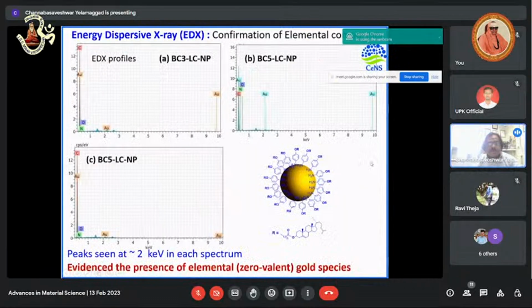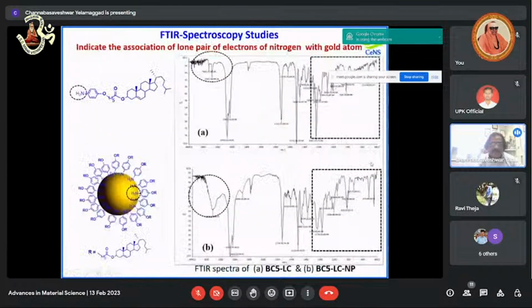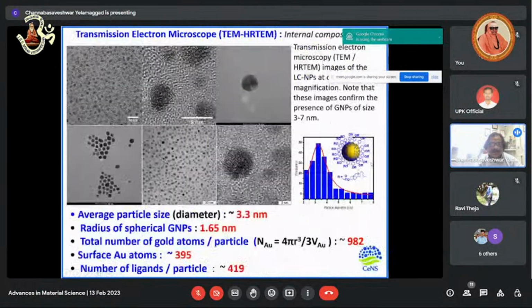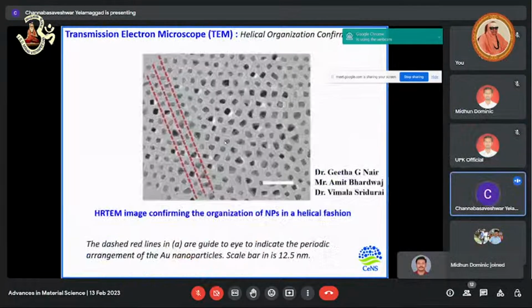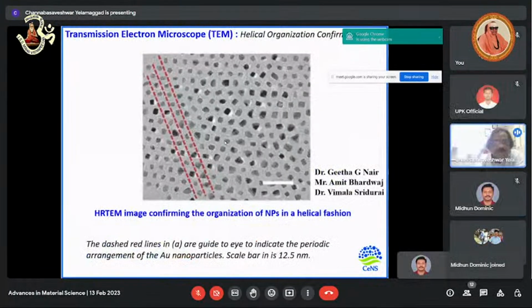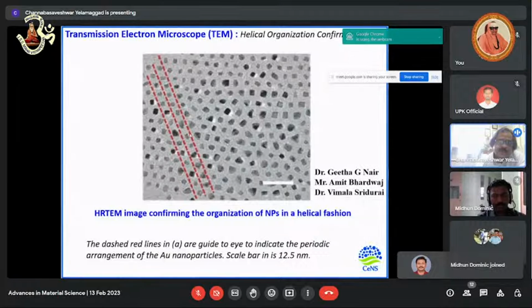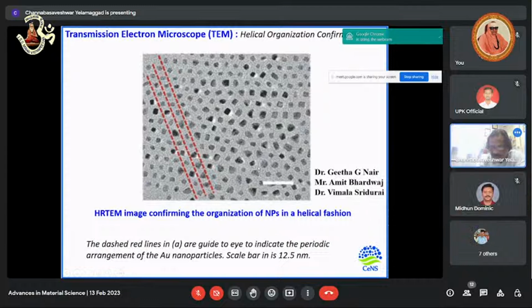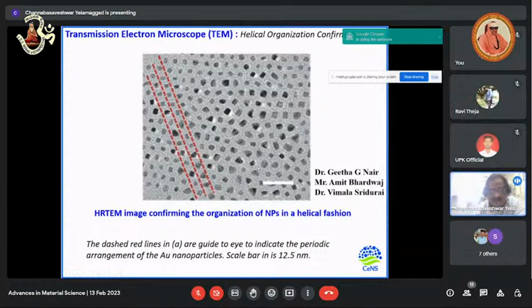We have characterized them using different techniques. I shall not go into the details of this characterization, but this is very important: HRTEM clearly established that the average particle size is about 3.3 nanometer. This is one of the very important slides as far as I'm concerned. You can see that once you burn off the organic molecule, you have the gold nanoparticle to which you have attached the organic ligands.